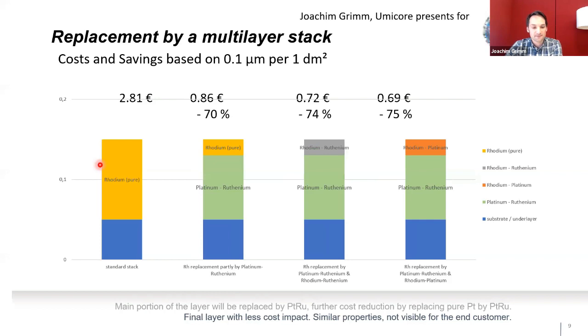Now we come to the point, we still have the rhodium pure on our standard stack. Rhodium pure comes to a price of €2.81 at such a thickness of 0.1 micron and 1 square dm calculated. So I said in level 2, okay, let's replace a big part of the layer sequence with platinum, and we do the pure rhodium on top. So why do the platinum in pure, if we can do a platinum-ruthenium alloy as an intermediate stack.